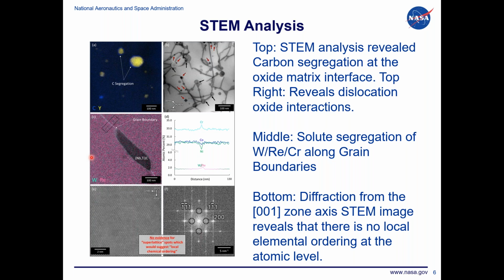And what we've also noticed is that in the matrix, we've added all these different elements, but they all still maintain this solid solution. We don't see any type of local ordering at the atomic level.